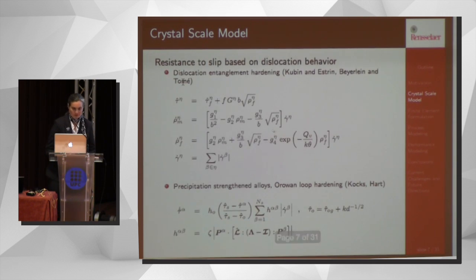So the hard part of plasticity is how these dislocations form and interact with each other. Now, the mobile dislocations are assisting plastic glide. You have to have a certain number of them for the glide to happen easily. If you don't have them, the material behaves somewhat brittly. The forest dislocations, the ones that are immobilized, are the ones that are hindering plastic deformation.